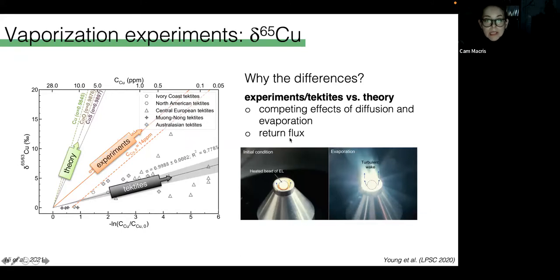our experiments. So in this photo on the left, we see a sample being heated. On the right, we see that the vapor phase is surrounding that molten sphere, leaving a turbulent wake as it travels. And what this tells us is that the vaporized material is interacting with the melt, and that some of that evaporated particles are likely recondensing onto and into the melt. So this phenomenon would lead to a larger alpha than what is theoretically predicted, which means less isotope fractionation.